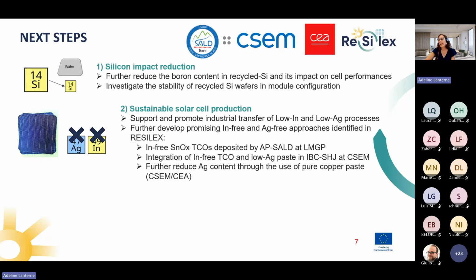Also at CSEM, they had very nice results and high efficiency IBC heterojunction solar cells without indium, so indium-free heterojunction IBC. And now their next step is to further reduce the silver content in these cells. Concerning the next step, one objective we know in order to have very sustainable production of photovoltaics in large quantity is to reduce the silver content down to 1 milligram of silver per watt. And for that, one promising approach that should be further developed is the use of pure copper paste.